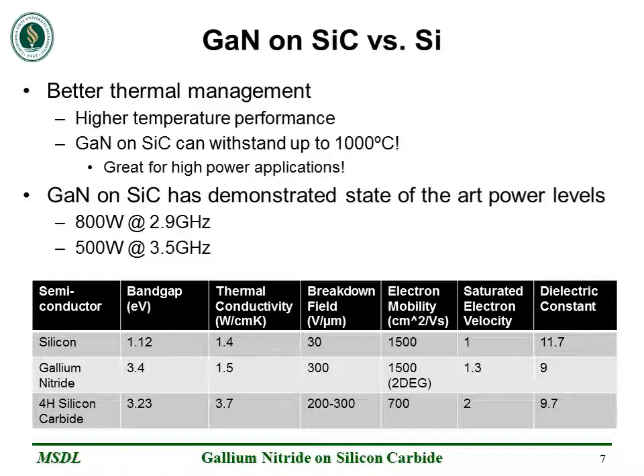Gallium nitride on silicon carbide offers superior thermal management over silicon processes. Gallium nitride on silicon carbide can withstand temperatures up to 1000 degrees Celsius. This is fantastic for high power applications. This technology has already demonstrated state-of-the-art power levels. 800 watts has been achieved at 2.9 GHz and 500 watts has been achieved at 3.5 GHz.